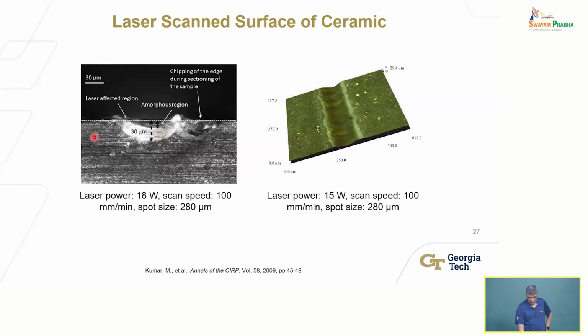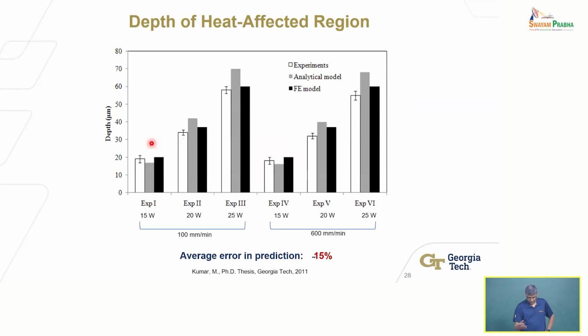But the region below it is weakened, but it's not amorphized, okay? That's what has happened. So now I look at this depth of the heat affected region. I can predict it using this model, right? Because I have a model which tells me what the distribution of radial stresses and circumferential stresses in this volume are for given laser parameters and scanning conditions.